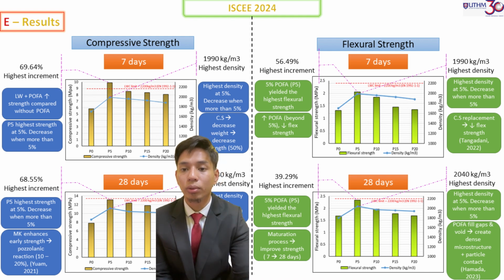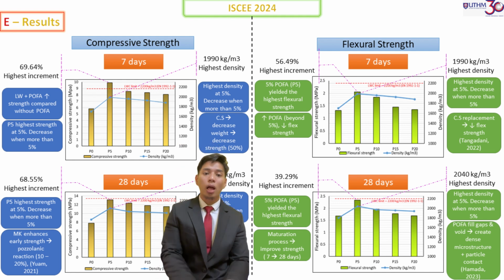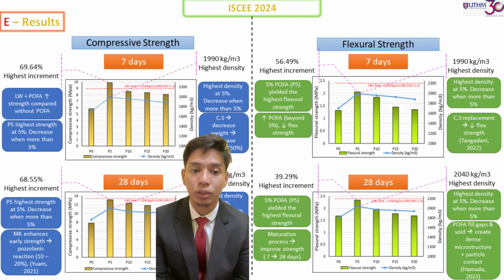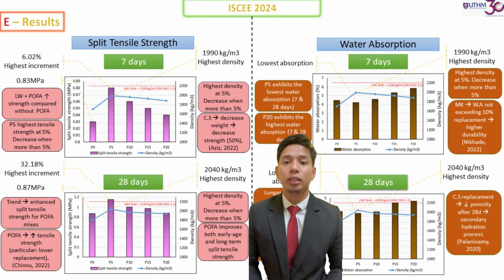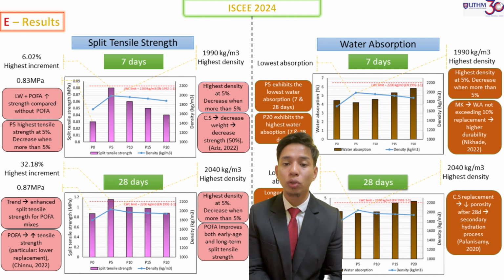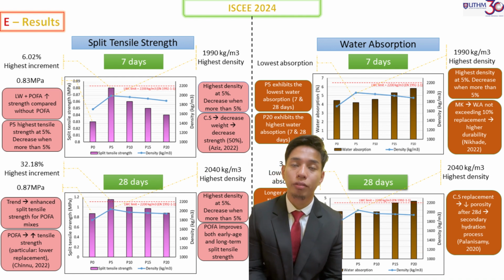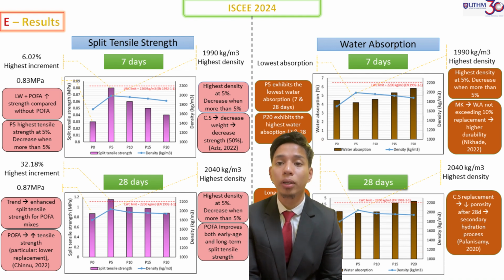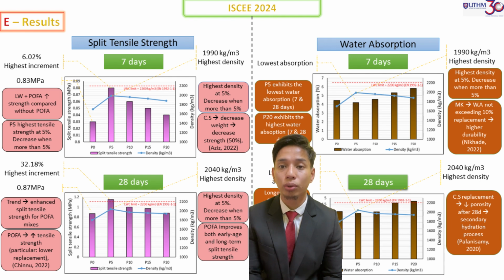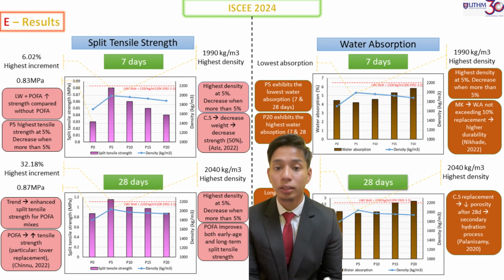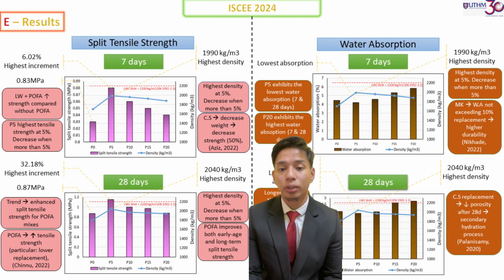And for the Metakaolin, incorporating Metakaolin into recycled coarse aggregate will improve the splitting tensile strength, compressive strength, and flexural strength. So next is the split tensile result. Same goes as the compressive strength and flexural strength. The highest split tensile strength belongs to the P5 with 5% of POFA as a partial cement replacement, with a 6.02% increment, which is the highest compared to the P0.